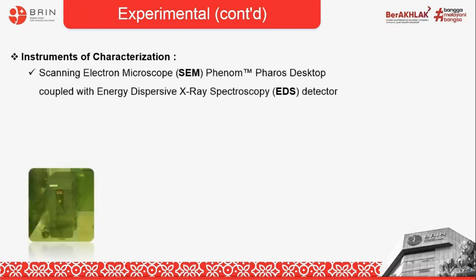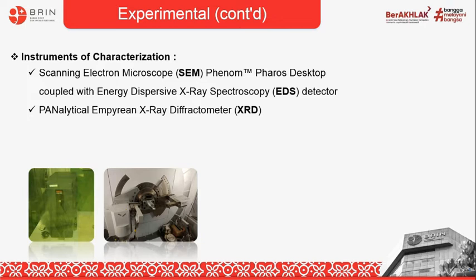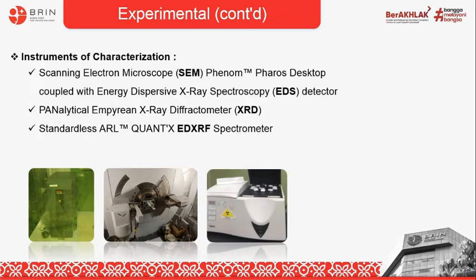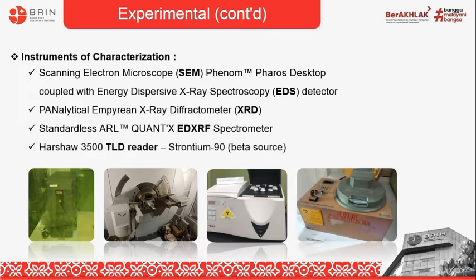A scanning electron microscope was used to observe the particle morphology of the powder. The elemental composition of several spots was also measured using the instrument with the EDS detector. An XRD was used to identify the phase composition of the powder, and the obtained diffraction patterns were then analyzed using the PANalytical ICDD database for HighScore. The XRF spectrometer was used to measure the dysprosium content of the powder. Analysis of the thermoluminescence profile was carried out using the Harshaw TLD reader after a low-dose beta exposure from strontium-90.